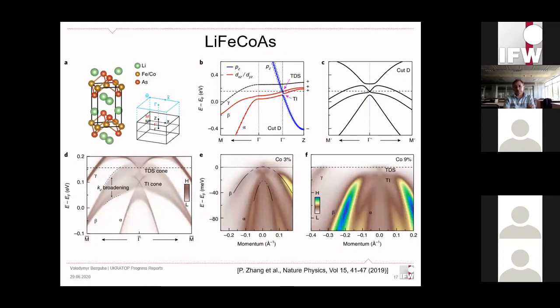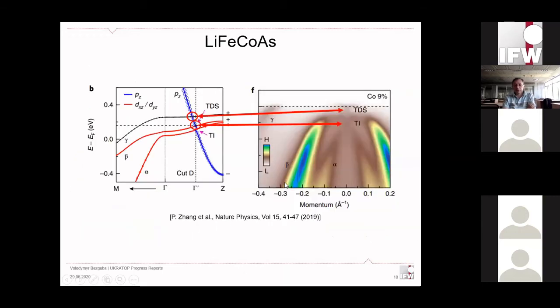In their paper, again, we start from calculations. There is again the PZ band, which comes from iron, and it dives very deep, crosses all of the bands. And here, indeed, we expect opening of the inverted gap, but on their spectra, it looks a bit strange because it looks more like the crosses they see with high cobalt doping correspond to Dirac cones, so to topological Dirac semi-metal cones, not to the inverted gap.